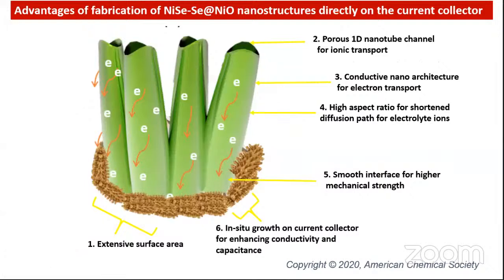Now, quickly coming to the advantages of fabricating the hierarchical structure directly on the surface of the current collector. One is we get extensive surface area, then we get porous 1D nanotube channels for ionic transport, the conductive nano architecture for electron transport, high aspect ratio for shortened diffusion path, smooth interface for high mechanical strength, and finally the in situ growth on the current collector enhances the conductivity and capacitance.